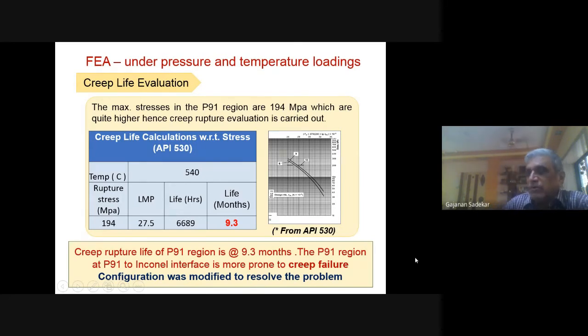After 6 months, sometimes 7 months, sometimes 10 months, that joint gets a crack. So actually the theory matched what was happening. It's very interesting. So creep failure occurs, and when we studied the microstructure, we found the creep-type properties, and that the creep phenomenon was occurring only at that particular location.